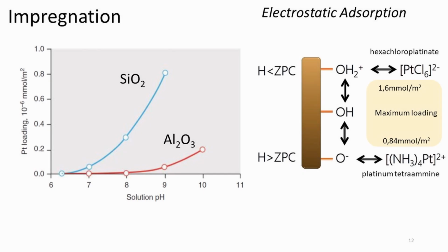The adsorbed amount of platinum on silica and alumina as a function of pH is shown in this figure. For silica, the platinum tetraamine ions adsorb extensively only above the point of zero charge of about 4. The maximum uptake on silica amounts to 6% of platinum, which is 0.8 micromole platinum per square meter. This can be attributed to the effective surface area of the platinum cation of 2 square nanometers per complex. The figure also shows that cation adsorption on alumina is not very extensive, and anion adsorption is used more often. Typically with alumina, chloroplatinic acid is used.